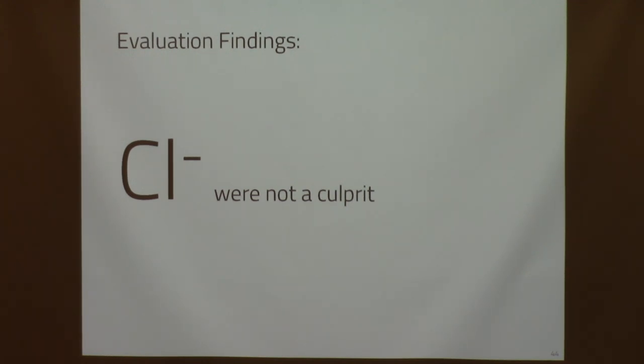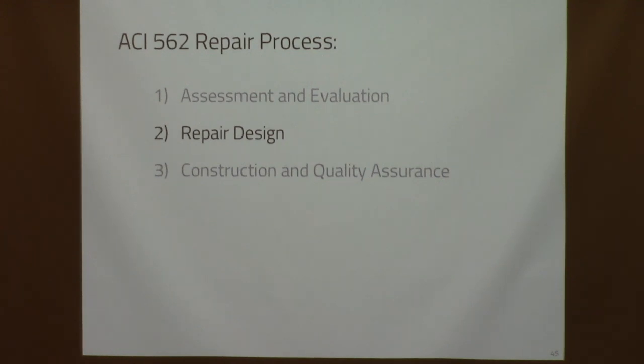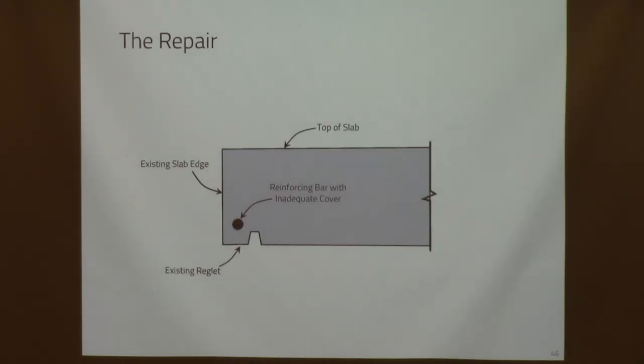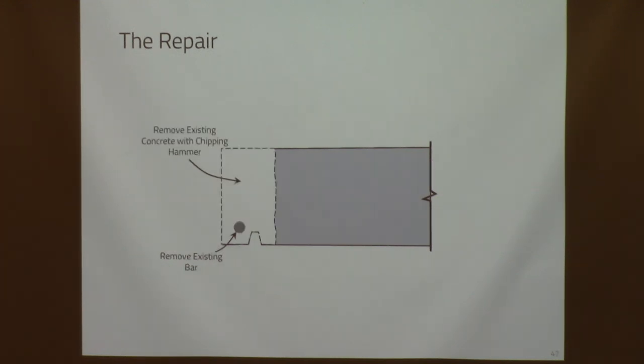And normally we think of carbonation-induced corrosion as something we never have to worry about because in industrial areas or concrete that's very heavily exposed, the carbonation front may take 50 years to move through there. But when you have a bar right on the surface, virtually a quarter inch of cover, a 16th of an inch of cover, it doesn't take long for carbonation to occur and to create a corrosion cell. So this was actually carbonation-induced corrosion. So repair design: we have that reinforcing bar with inadequate cover. And what are we going to do about that? Well,